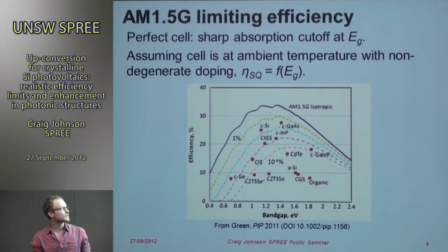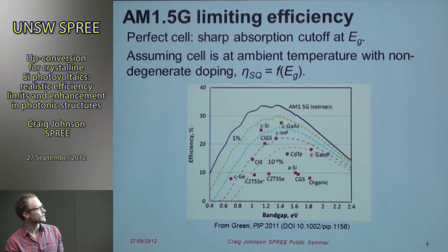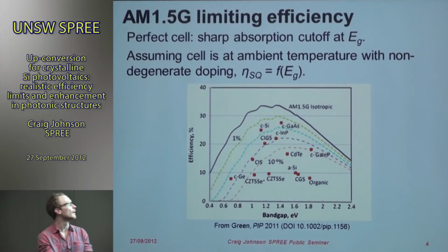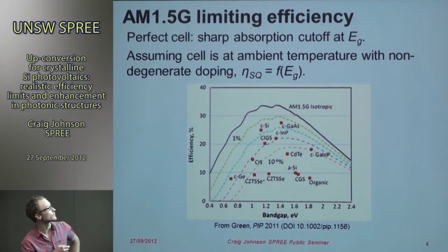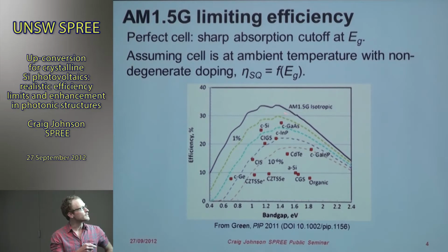And it's shown here, in particular, from a recent paper by Martin, where he calculated the conventional efficiency limits for the new revised spectrum. And so what we see in the solid line is the Shockley-Queisser limit for a conventional solar cell under the terrestrial spectrum. And then these other curves really correspond to the same thing but calculated with worse radiative efficiency.